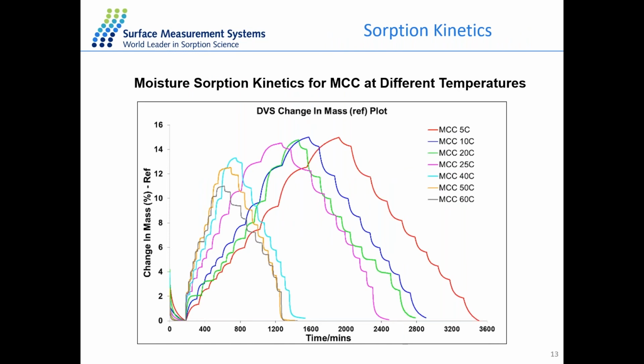And here are the results for the water sorption data at different temperatures. Different colors correspond to different temperatures, and between 5 degrees and 25 degrees, the moisture uptake at a particular relative humidity doesn't show a significant difference. For example, at 95% RH, which is the top point here, the water uptake for all different temperatures is around 14 to 15%. But the time to reach equilibrium is much longer at lower temperature. For example, at 5 degrees, the full sorption-desorption cycle will finish around 3 days, while for the 25 degree experiment, it just takes about 1.5 days.